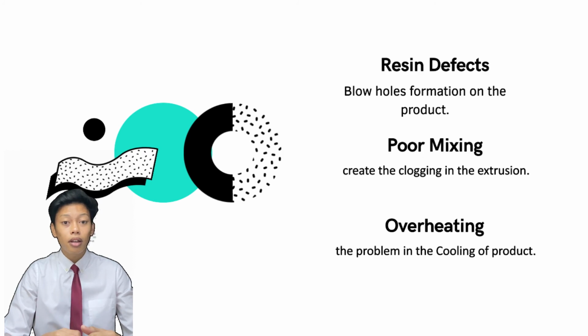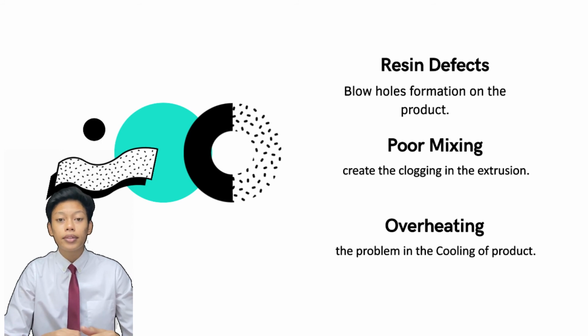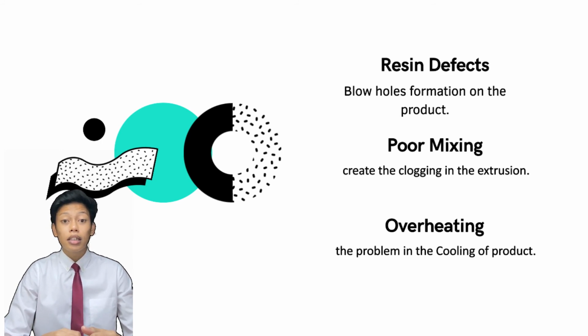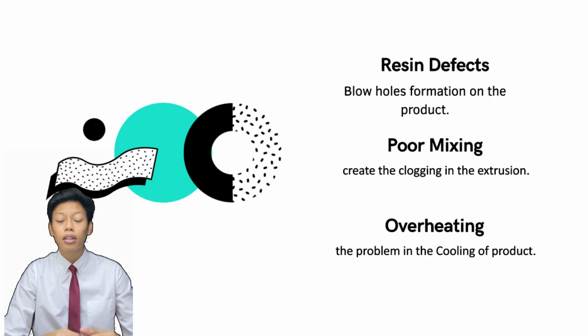Last but not least, overheating. Melt occurs in a single screw extruder primarily as a result of shear heating of the polymer. Shear heating is the result of a polymer-filled screw rotating within the barrel. Overheating may produce degradation of the polymer material or make dimensional control and sizing difficult, and it can create problems in the cooling of the product.